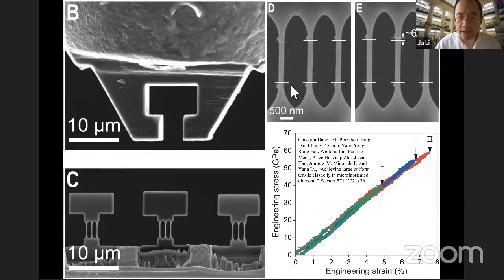So what we have here is a microbridge that is several microns long. And furthermore, we have 3 of them together. And we pull it up to 5%, up to 7, 8% together. And this is also not a nanowire. This is actually just using a focused ion beam to sculpt it. So this demonstrates the possibility that it may be scalable to wafer scale to have arrays of these microbridges, and each microbridge may contain thousands of transistors, because right now the transistors are below 10 nanometers in size, or quantum sensors in one of these bridges.